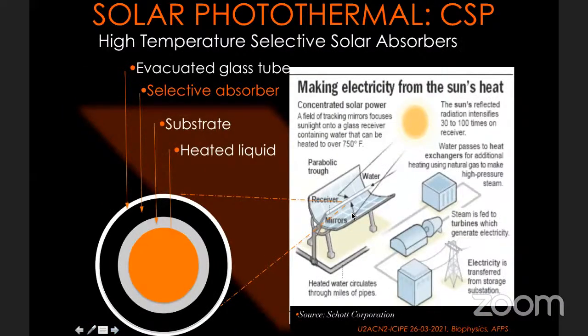Just to see clearly how it works, here is the tube at the focal point of the concentrated solar mirror. The radiation is concentrated on the receiver, and the receiver in effect is a tube. Here, copper or stainless steel or aluminum, but mainly stainless steel or copper. And inside there is water or oil, but water generally speaking. And this stainless steel is coated with a black material. And this black coating has to absorb as much as possible of light from the sun and near infrared and convert it to heat, and that heat goes through the substrate to the liquid, or the oil, to heat it, and therefore to go to the normal turbines and so on to generate electricity.